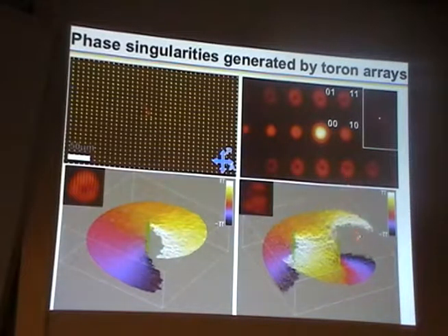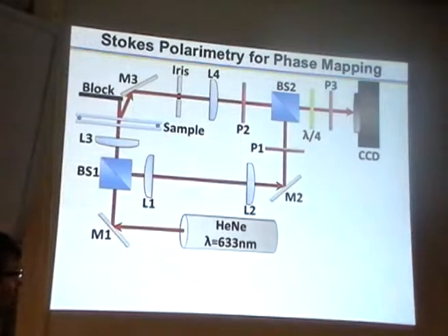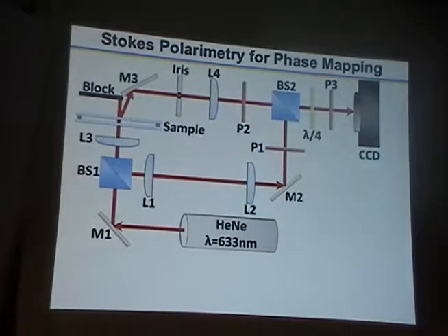Right, so now if we go to the second order, we would note that we have more than just an elementary screw dislocation in the phase of light, right? The Burgers vector of those dislocations is increasing. And so you can see that we can also control the charge of the optical vortex that we generate.